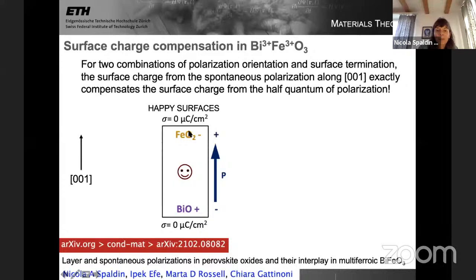So here is my bismuth ferrite thin film. I've chosen bismuth oxygen at the bottom and FeO2 at the top. And so the bottom has an internal positive charge and an internal negative charge at the top. The polarization is opposite. The spontaneous polarization is negative at the bottom and positive at the top. So these cancel, and we have completely happy, electrostatically stable, compensated surfaces. There's no driving force for this bismuth ferrite thin film to form domains or to reverse its polarization.